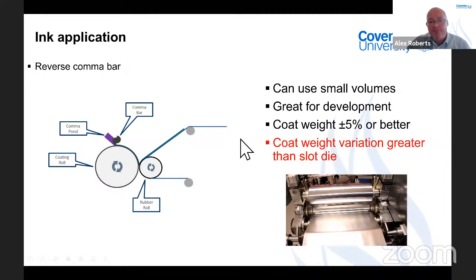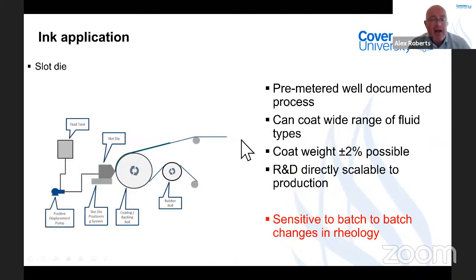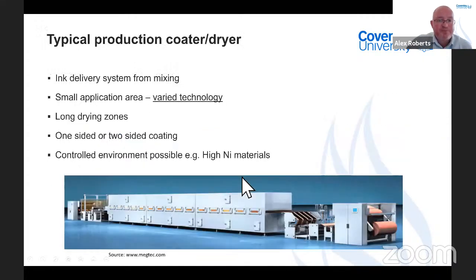More common industrially and in production, in fact, almost all coaters industrially now are based on a slot die application. So this is more of an extrusion process, which gives exceptionally good control of the electrode that's produced and the thicknesses and reproducibility. And it's a very well-metered and documented process.